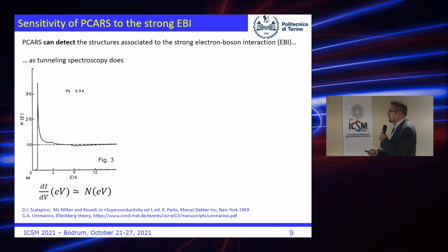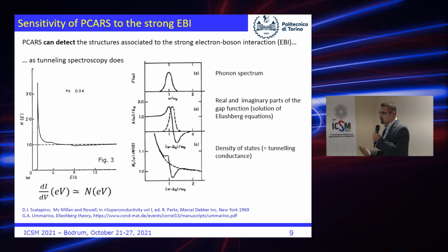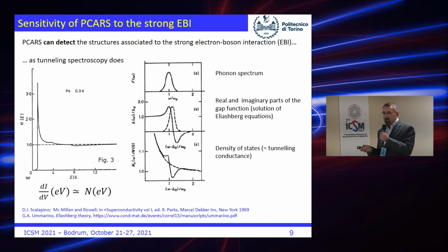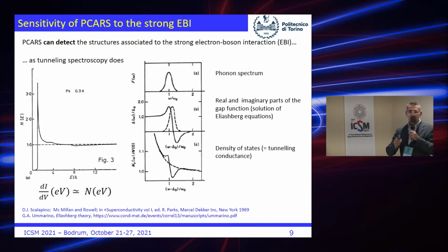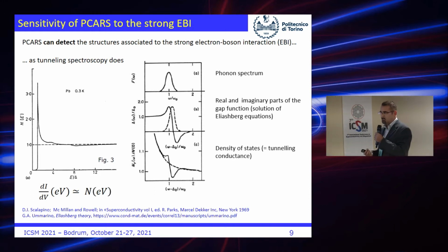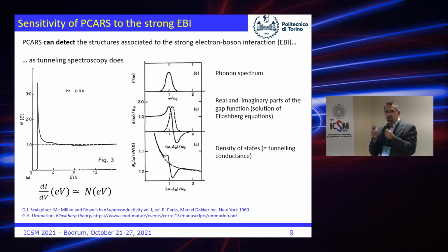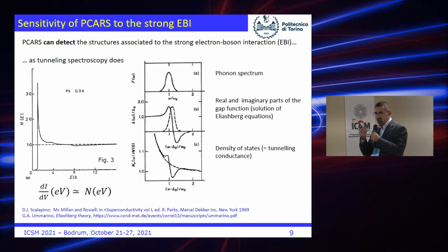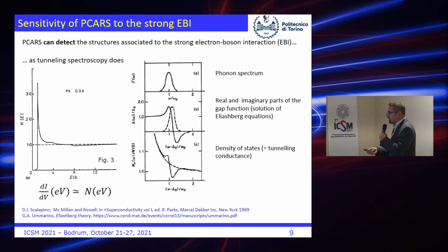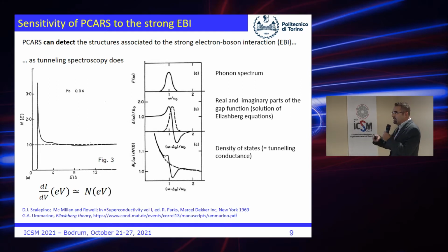To understand how this can happen, let us start from a very simple example. Suppose that the phonon spectrum consists of only one peak, and we have to calculate how this peak can give rise to structures like this. Well, this happens only in the case of strong coupling, so we cannot use the BCS theory, we have to use the theory for strong coupling superconductivity, that is the Eliashberg theory. Within the Eliashberg theory, the gap is not a constant, but is a complex function of the energy that has an imaginary and a real part. So, with this, we can solve the Eliashberg equations. We get the gap. This is the real part, and this is the imaginary part. With this gap, we can calculate the density of states, and it turns out that the DOS has really a structure that is the remainder of this.